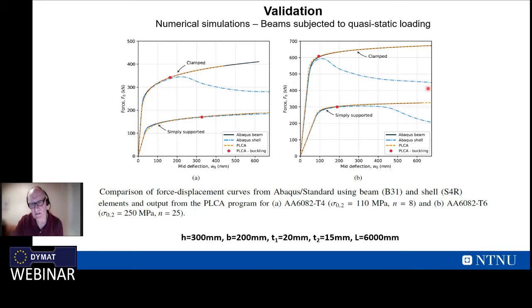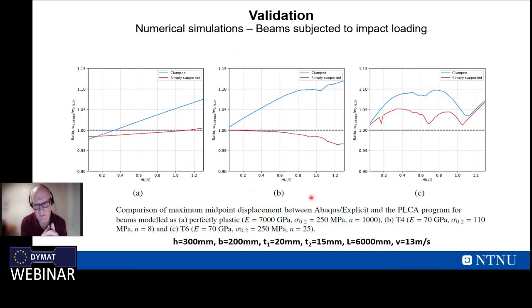And this is the same for a T6 alloy, where the yield stress is 250 and n equals 25. Still, the force displacement curve is well represented, and the analytical model gives quite good predictions of when buckling takes place. We have also done some studies linked to comparison for impact. Here is the ratio between the Abaqus displacement and this simplified model using the mode approximation technique as a function of mass ratio. And for tempered T4 and T6, we are within plus minus 10%. So from a design perspective, this looks quite promising.